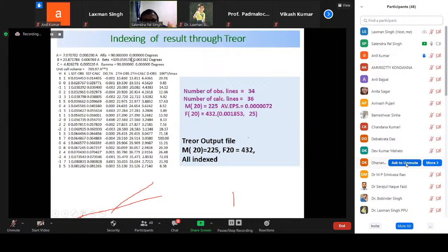Now comes the question of finding the space group. That is another challenge. In order to find the space group, first you have to find the lattice type, whether it is primitive, body-centered, or C-centered, or what kind of lattice is present. So by indexing, what we infer is that we got the lattice parameters A, B, C and the beta angle, and we know that the crystal is monoclinic, and all peaks are indexed. So we have all the HKL planes, and we can calculate the d spacing.